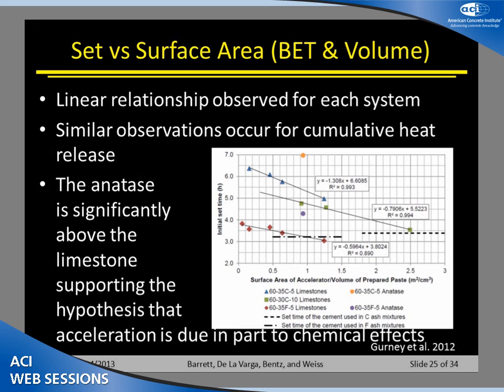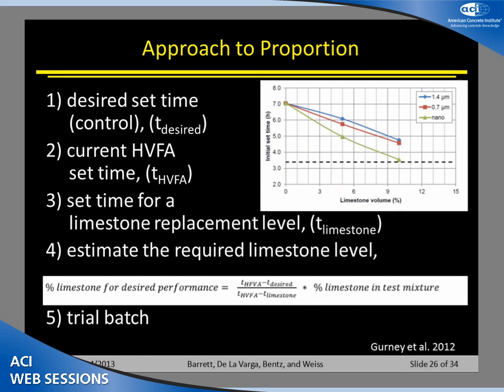So if we can use finer limestone powders, we can get back to a set time that's really more compatible with conventional processing. What you can see here is that if we're using a 5% limestone or 10% limestone and that limestone is very fine, it's very possible to get back to something equivalent to that 100% OPC system in terms of setting. So we can now overcome some of those delays in set just by combining limestone and fly ash in that system, because of the beneficial effect of the limestone reaction that's going on, but also the fine particles that are leading to some nucleation.